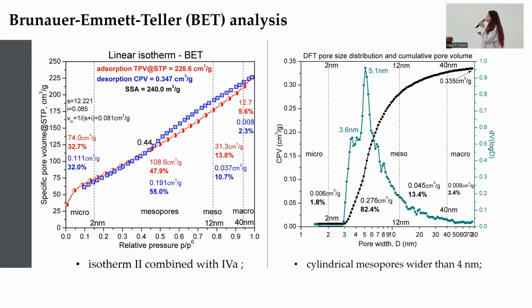Then we performed the BET analysis. We can see that the adsorption isotherm has a hybrid aspect, with isotherm 2 combined with 4A. The elements for isotherm 2 can be seen at the extremities, describing the monolayer adsorption limit, and the elements for isotherm 4A are described by the hysteresis loop, describing therefore the monolayer adsorption combined with capillary condensation in cylindrical mesopores wider than 4 nanometers. After the pore size distribution analysis, we can see an interval between 2.5 nanometers and 50 nanometers, almost Gaussian, centered at 5 nanometers, with a majority of pores less than 10 nanometers.